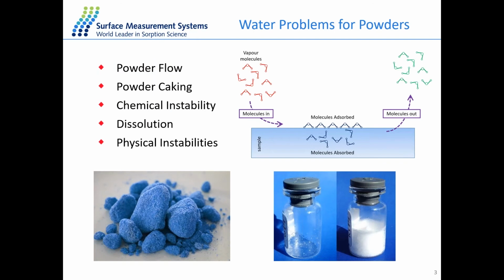So moisture is everywhere in the real world, and it can cause lots of different problems for different samples. For example, for powder samples, it could cause caking of the powder and affect the flowability of the powder. And also, the moisture in the vial on the right-hand side will lead to the dissolution of the freeze-dried material, and that will affect the application of the sample. So it's quite important to study the moisture sorption behavior of those kinds of pharmaceutical products, and DVS could be a really useful tool to modulate or simulate the conditions for the storage of the material or during the application.